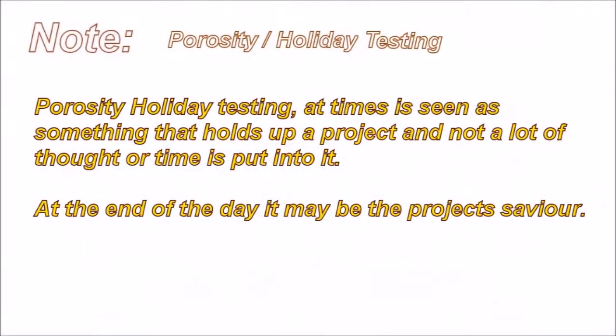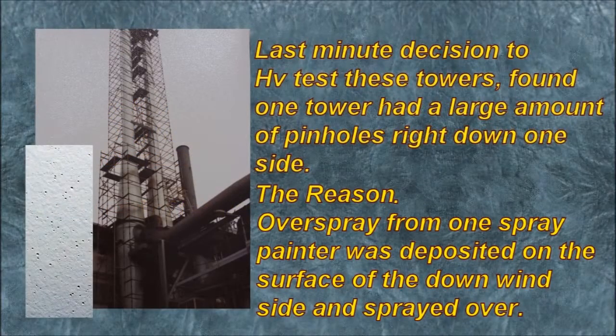Porosity holiday testing at times is seen as something that holds up a project and not a lot of thought or time's put into it. At the end of the day, it may be the project's saviour. A last minute decision to high voltage test these towers found one tower had a large amount of pinholes right down one side. The reason? Overspray from one spray painter was deposited on the surface of the downwind side and sprayed over by the second painter.